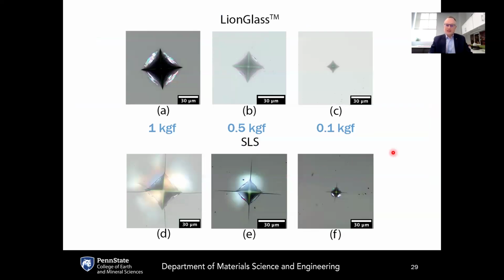This shows you some indentation results for LionGlass on top and for soda lime silicate on the bottom. This is 1 kilogram force on the left, 0.5 kilograms force in the middle, 0.1 kilograms force on the right. You can see that for soda lime here, it's cracking even under the lower load of 0.1 kilograms force, and you get really significant cracks at these higher loads. With LionGlass, we don't observe any cracking at any of these loads.